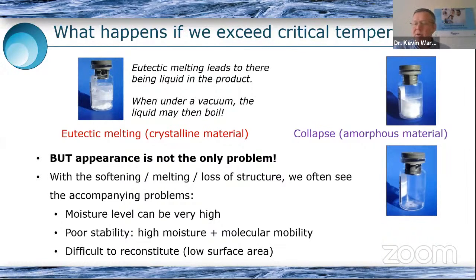Well, you might say, for my product, maybe appearance is not particularly important. Well, that might be true, but often what we find is that if something's lost structure, then that tends to bring with it other problems. And so the moisture level can be very high. So in this glucose sample, you can probably appreciate that we're not down to very, very low levels of water. It effectively looks like a syrup, so maybe it's 10% water, possibly even more. Well, that's probably not going to be stable for a very long time. If it's got poor stability, then that could also mean that the molecular mobility is higher, and so there could be other interactions happening. And low surface area means it's going to be difficult to reconstitute. So no, appearance is not everything, but we do tend to find that if the appearance is bad, then other problems seem to follow.